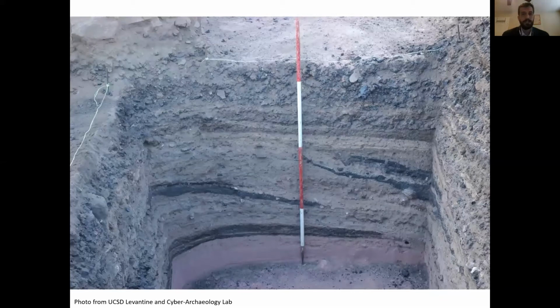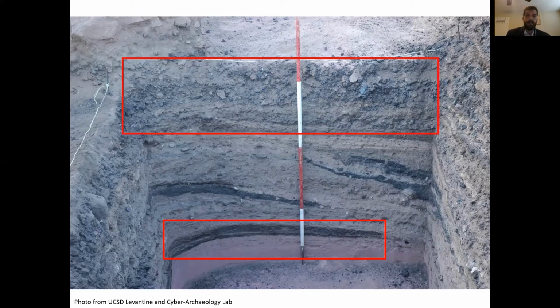I just want to look a bit closer at the slag mound excavation briefly and point out that directly above the bedrock, the reddish soil at the bottom of the section here was a thin accumulation of crushed slag right here in red. It was 5 to 10 centimeters thick, and this provided evidence that the site was producing copper basically right from the outset, although perhaps on a small scale, given that it's just a thin accumulation. But over time, this scale of production increased based on this thicker accumulation of slag at the surface of the excavation. And we will compare this to the 2014 results, so just keep this in mind.